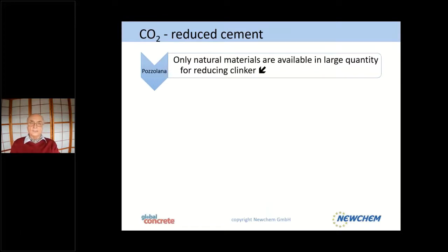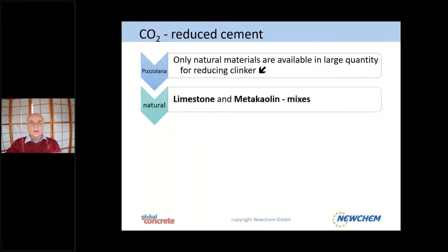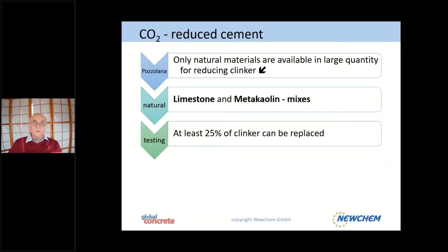Now, as we have heard in different conferences, natural materials are the only thing which is available in large quantities, and therefore you can reduce your clinker. We have done some trials with mixes of limestone and metakaolin, which I'm going to show you. We can replace at least 25 to 30% of the clinker, so reducing the CO2, because neither the milled limestone nor the metakaolin by itself liberate any chemically bound CO2.